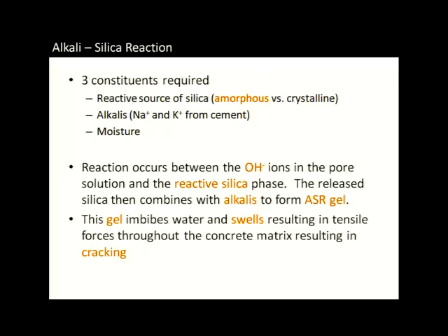And this is your little blip on chemistry. The reaction is occurring between the high pH that we have in concrete. So concrete pore solution is around 13.5 to 14, so very, very high pH, very much like Drano. And the hydroxyl ions that are in that pore solution attack these certain reactive phases in the silica. They liberate the silica into the pore solution. That silica then combines with the alkalis, the sodium and potassium that are coming from the cement to form this gel. And this gel has a high affinity for water.